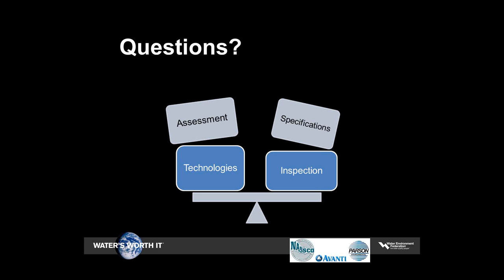Well, as I believe Jim went over that during his presentation, but there's several things that are happening. Basically, the bacteria that is present in the manhole is feeding, and it's creating hydrogen sulfide gas, which is typically what people think is actually causing the problem. That's creating a smell, a rotten egg smell, but it's not actually the problem. The problem comes when that bacteria converts that into sulfuric acid. And the sulfuric acid is actually what is attacking the paste of the concrete and deteriorating the structure.